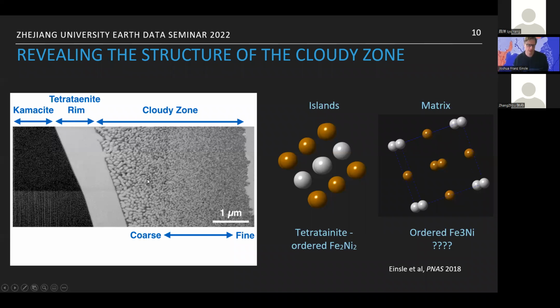However, to understand whether or not these individual islands of tetrataenite, which are on the order of 100, 150, sometimes up to 200 nanometers in size, are actually recording magnetic fields, we need to understand something about the nature of the matrix, which is this black structure in the cloudy zone region. It's a different material than kamacite. And we had indirect evidence that suggested it was an iron-3 nickel in an FCC-like lattice that you can see here. But we weren't really sure.